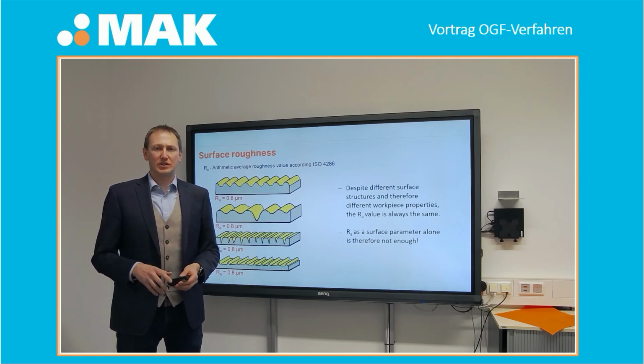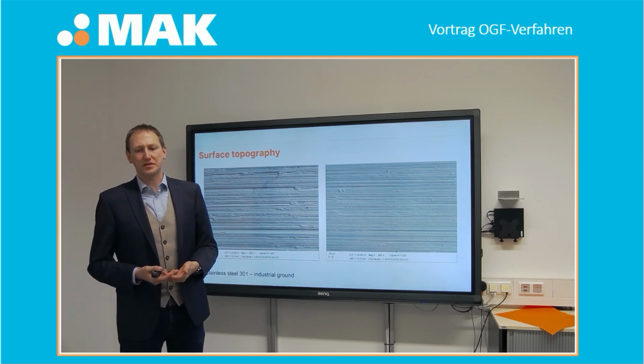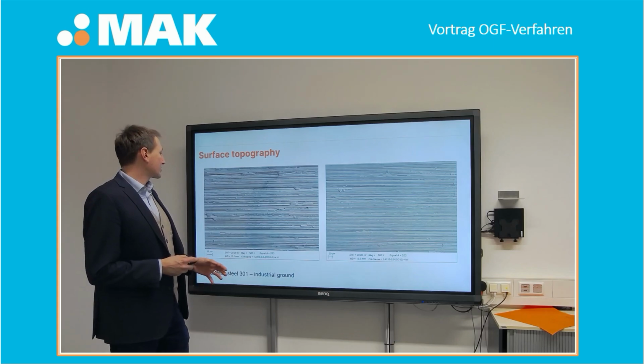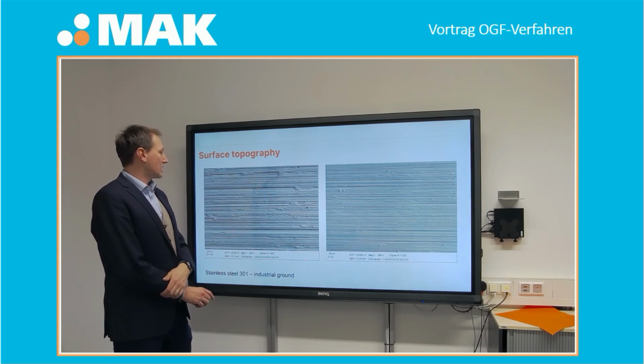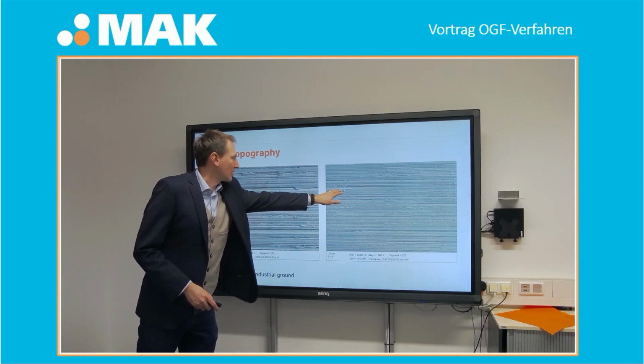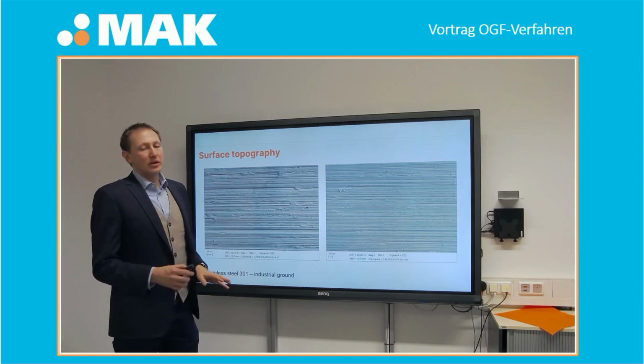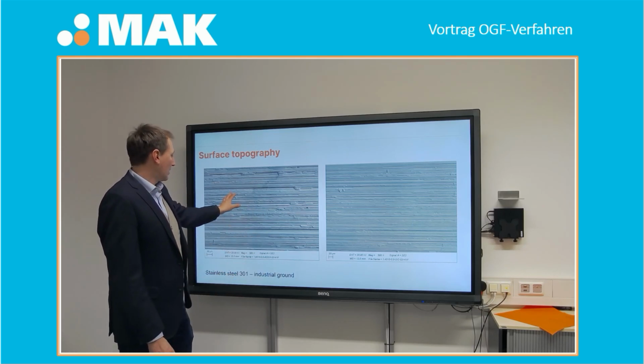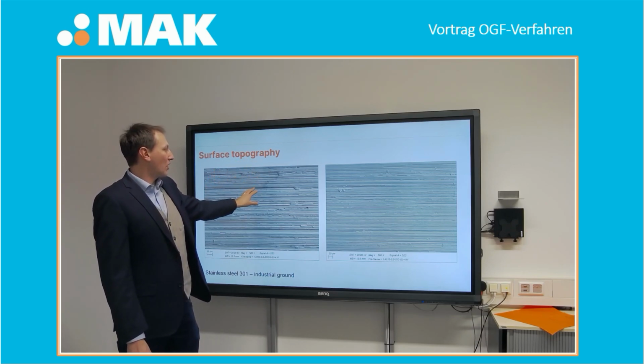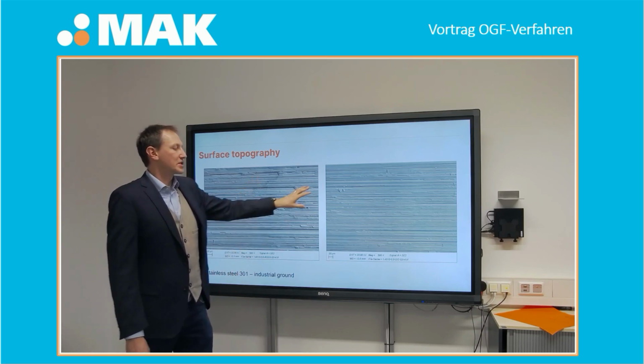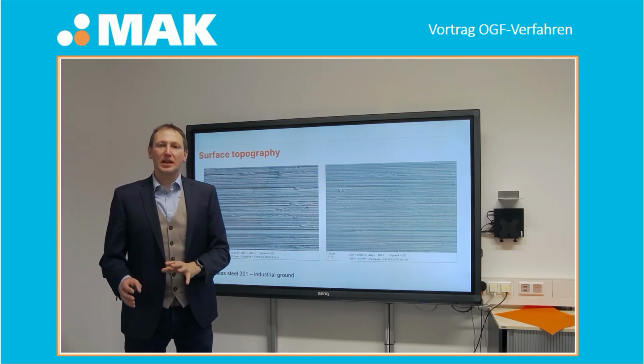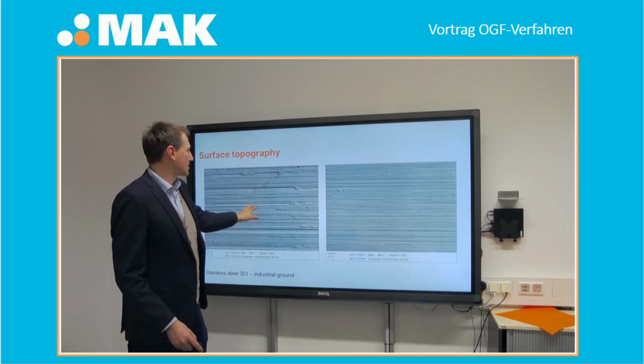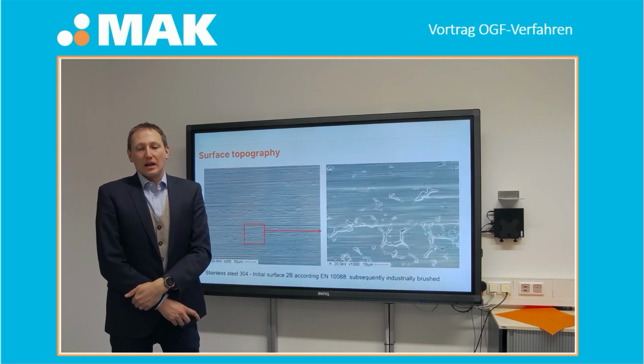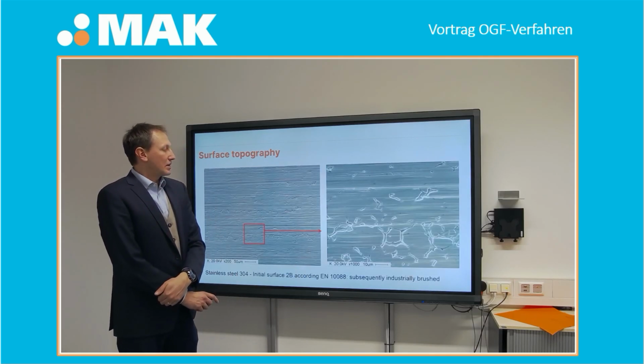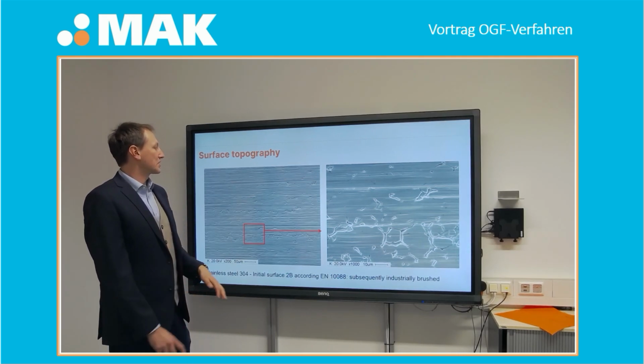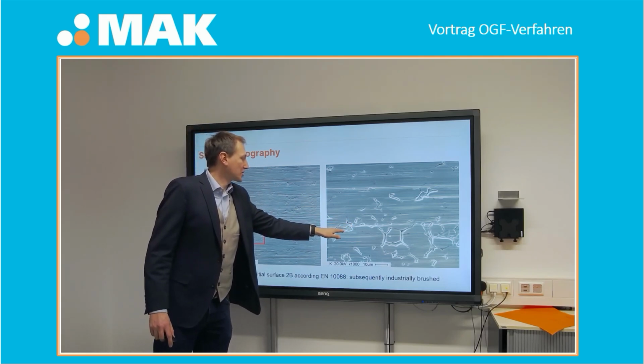And if we take a closer look at a surface, maybe a ground surface, like shown here, industrially ground 301 stainless steel, you can see we have different surface properties, and different chips left on the surface, depending on the kind of surface preparation. The left side was done with an aluminum oxide grinding abrasive, the right side with silicon carbide. Even with the same grinding parameters, you can see you have different kinds of surfaces. And if you add some additional machining like brushing, in a closer look you can see microstructures left on the surface.